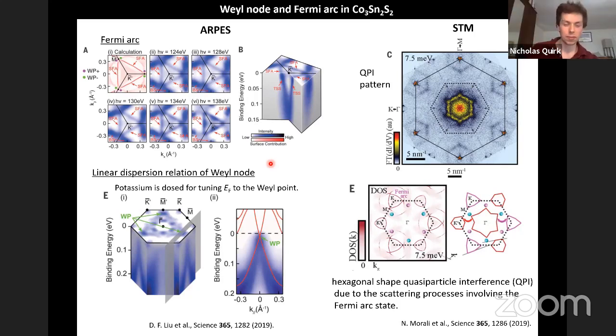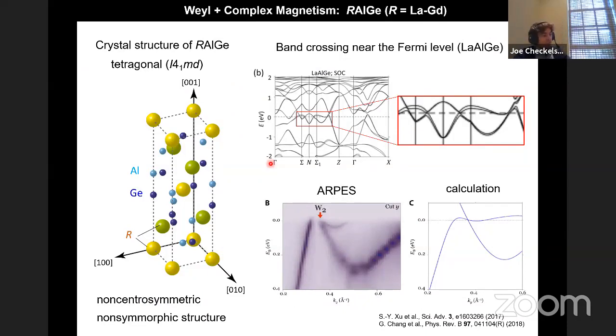Cool. And our final question for this first talk will be, do f electrons play a role in the transport or electronic structure of cerium aluminum germanium? Yes, so it's an excellent question. So typically what one thinks about in these f electron systems is normally you imagine that the f electrons, especially if it's something like gadolinium, typically the f level is pretty far away from the Fermi level and locally contributes magnetism. And then it's the other electrons in the system which are associated with the conduction and valence bands, which are near the Fermi level. A lot of times with cerium, that is not the case. And cerium does an interesting amount of mixing with the f electrons and with the conduction electrons in these systems. And you can get f-s or f-d hybridization in these systems.